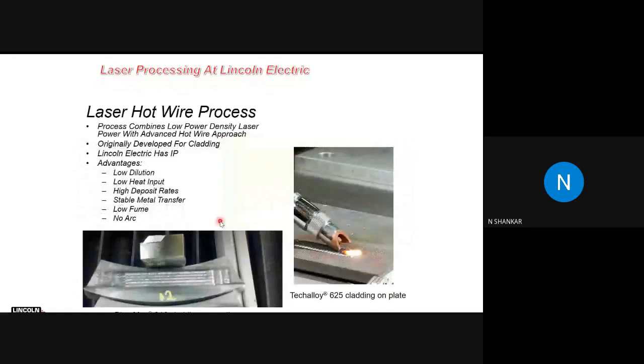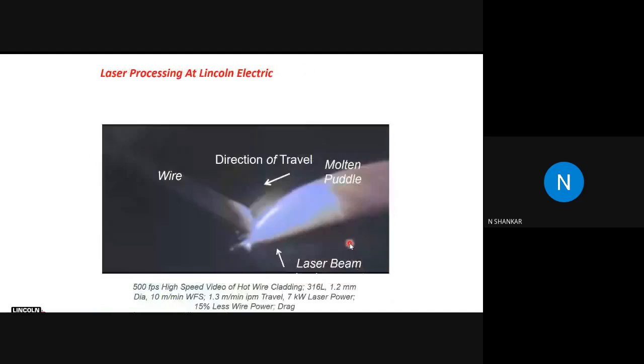We are also working on hot wire laser process, which is basically for the cladding applications. It will give you low dilutions. In cladding, your most important requirement is low dilution, low heat input, and you want a higher deposition rate. So all this is possible with the laser hot wire process. We have done a lot of cladding applications. You can see over here, the Techalloy 625 consumable is used for hot wire cladding applications.